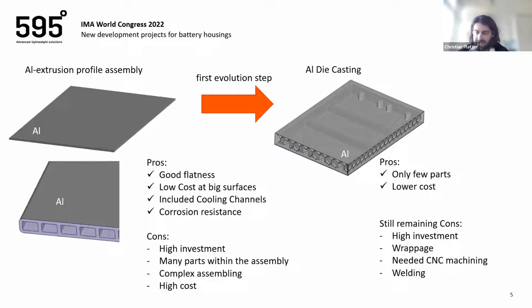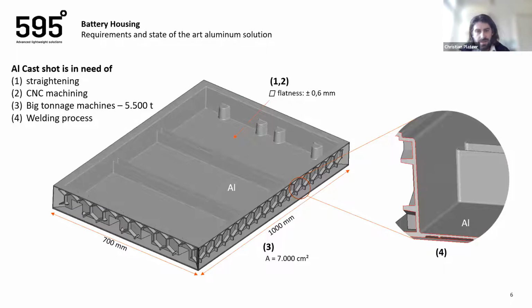You still have a high investment in very big machinery. We have dross from the casting that we somehow need to deal with, and to close the cooling channels, we need a welding process. So this is an example for a rather small battery housing with a dimension of 700 millimeters to 1 meter. And the requirements that we need to meet is, for example, flatness of plus minus 0.6 millimeters in the contact surface to the battery cells.